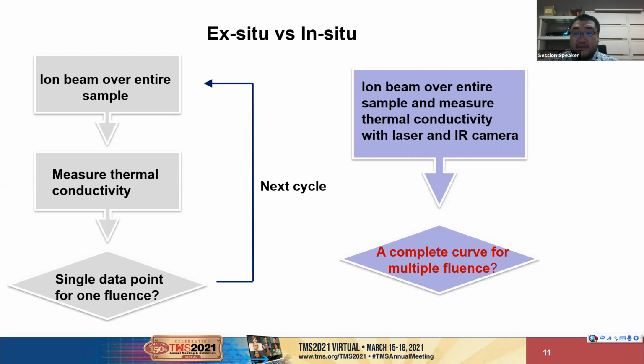And for the in-situ measurement, you don't have to go through that complicated process. What you need to do is similarly irradiate the sample in the traditional way, but simultaneously measure the thermal property during the radiation. Therefore, after you complete the radiation damage experiment, you're going to get a complete curve for multiple fluences, which saves a lot of time and makes it much more efficient.